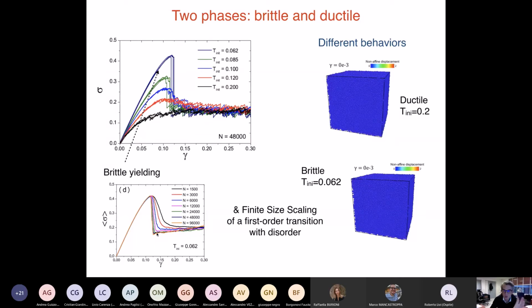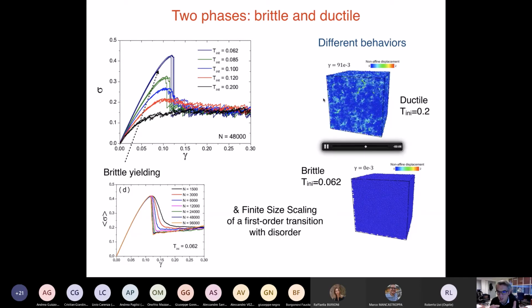Now, it's also interesting to see that these two different ways of yielding, smooth versus discontinuous, correspond in real space to two very different phenomena. So here is what you find in the case of the ductile behavior. So this is this line here. When the system is not very well annealed, what I'm showing is the non-affine displacement, the part of relaxation. Let's think that it corresponds to plastic behavior. And you see that the system is relaxing in a more or less uniform way.